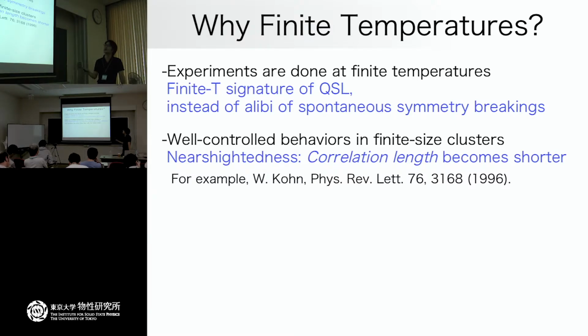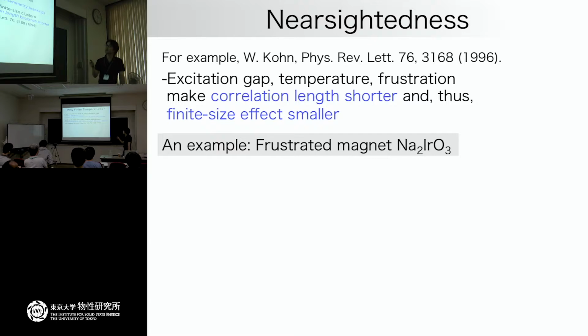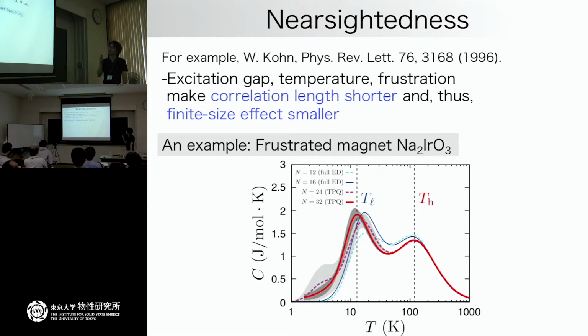And it was already discussed by Walter Kohn many years ago. His motivation was about nearsightedness in ab initio calculations. For example, if you calculate semiconductors, then usually the electrons' behavior is determined from the really local nature of the crystals. This is the origin. But if you look at frustrated magnetism, still the correlation lengths become really short at finite temperature. So thanks to this nearsightedness, the size effect becomes not so severe.